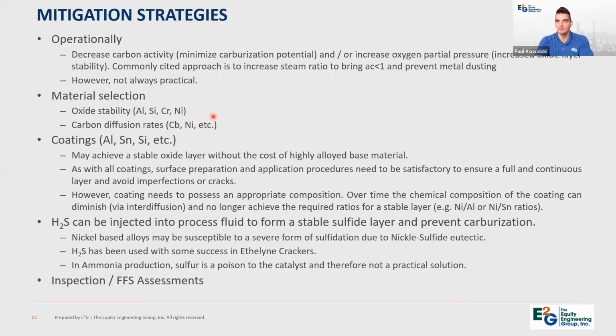Another very common approach is to install coatings. Based on the environment and base material of construction, there are many different coatings that you could choose, some being aluminum-based, tin, silicon, etc. And really the goal with the coating is to achieve that stable oxide layer without the added cost of including the high alloying additions into the base material. It may be a lot cheaper to install a thin coating versus upgrading the entire material.